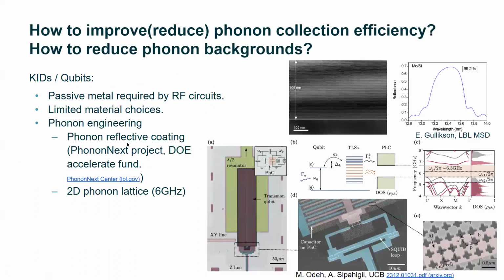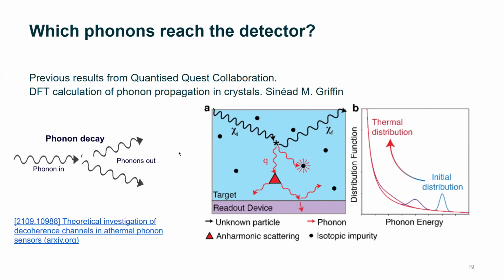So first, starting from the phonon reflective coating. First question to ask: which are the phonons reaching our detector? Phonons propagate, and they also decay. The decay rate is actually pretty fast for the high energy asymmetrical phonons, and then the decay rate decreases as the phonon energy decreases, and finally they reach more or less a free streaming state. You can consider different types of phonon decay. It can decay on the surface. It can go through harmonic scattering. It can also decay on the isotopic impurities in your crystals. So you start from an initial distribution at high energies, and then slowly approach this thermal distribution.